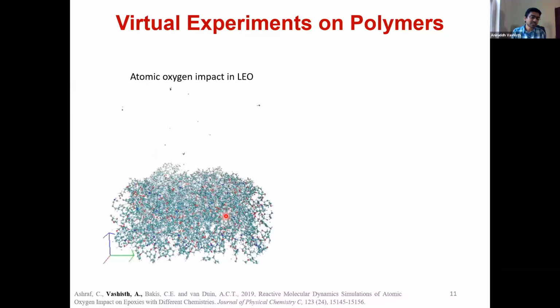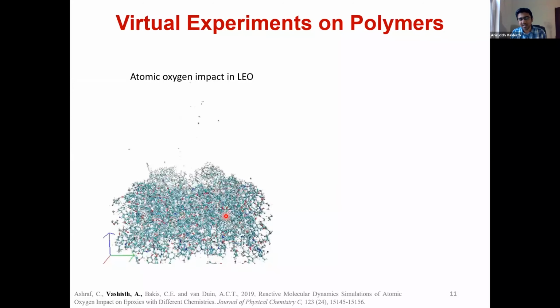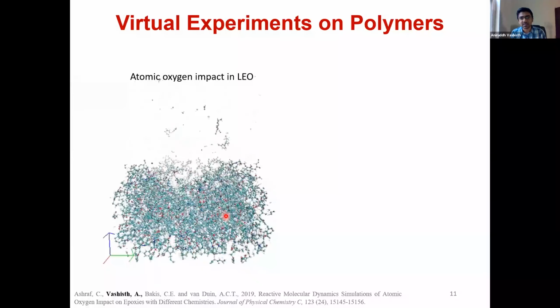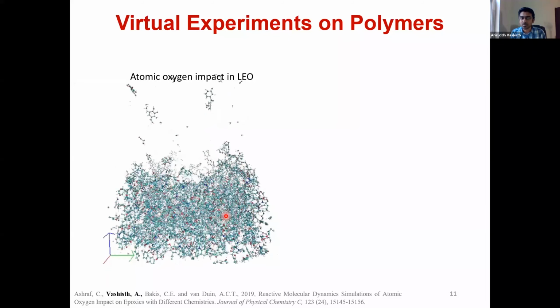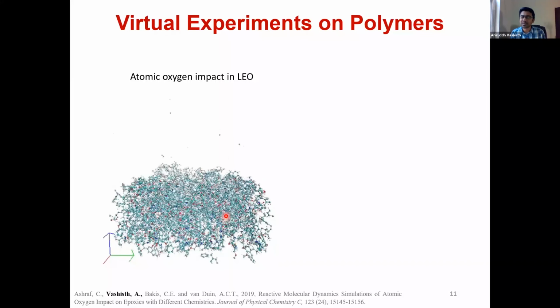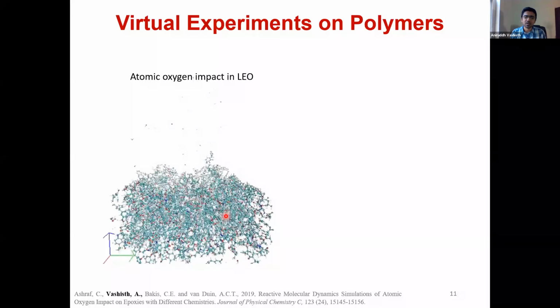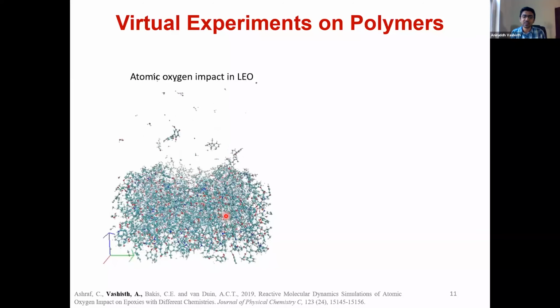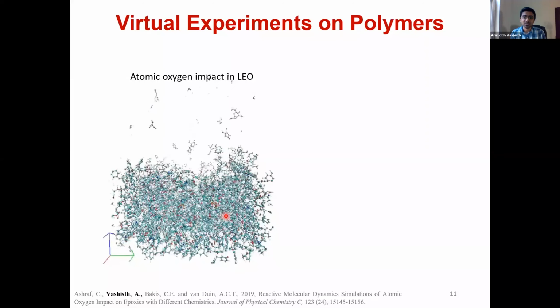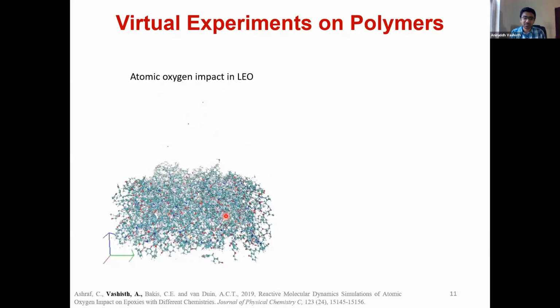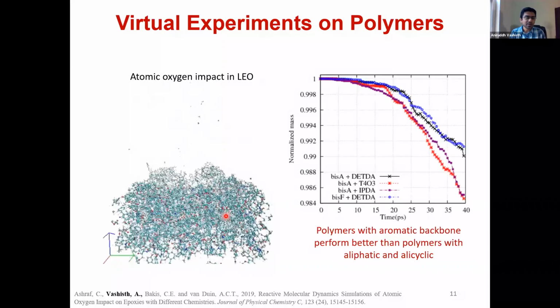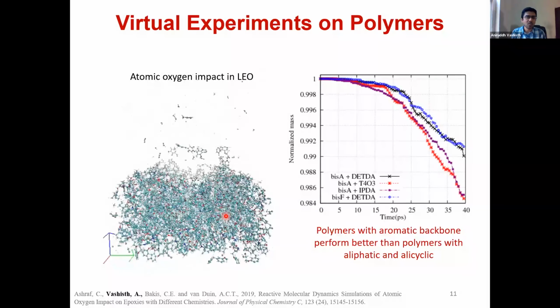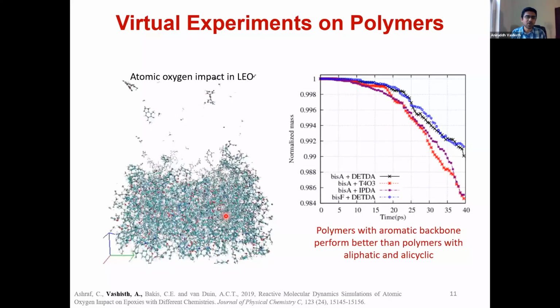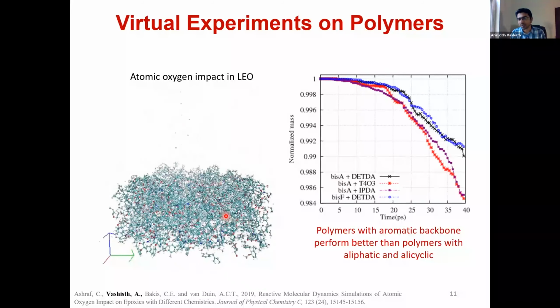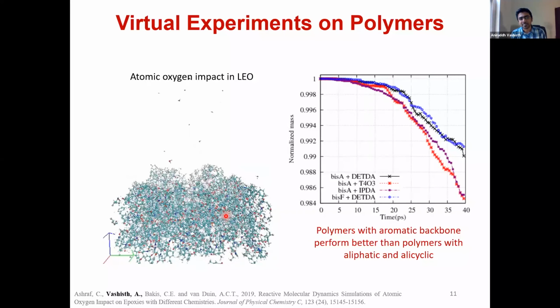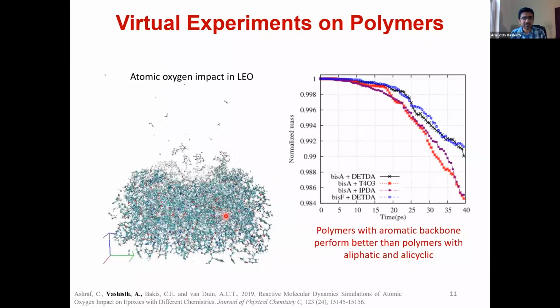Now, there are some experiments that are terribly difficult to do in the lab. For example, atomic oxygen impact on polymers which are in lower Earth orbit. This is going to be a really difficult experimental setup in your lab, because you need atomic oxygen traveling at a speed of 8 kilometers per second. So that's going to be terribly difficult, but through simulations, this is something that you can do and try to get some insights as to how a polymer behaves. Like, how does the polymer chemistry affect, or how does the polymer backbone get affected by atomic oxygen impact.